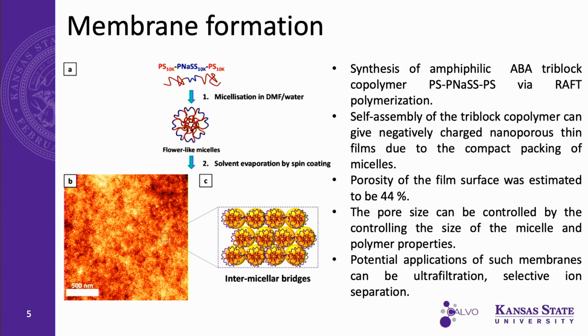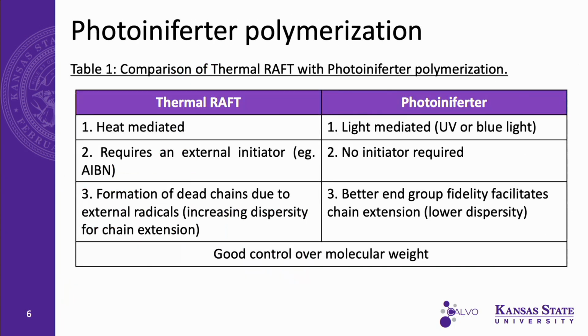The spaces between these micelles are what were the pores, and the porosity of the film surface was estimated to be 44%. The pore size can be controlled by changing the polymer properties, and such membranes have potential applications in ultrafiltration and selective ion separation.